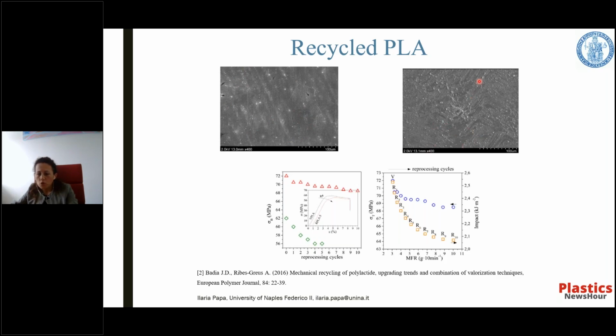The micrographs show a loss of orientation of the processing line in recycled PLA, which is present instead in virgin PLA. Furthermore, the surface is less smooth and more prone to mechanical scratches.